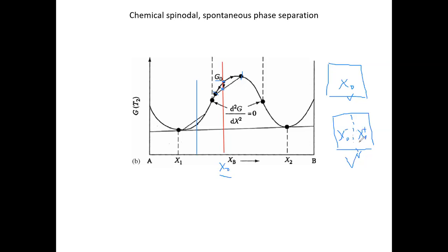Now you can clearly see that if our composition is this given composition, X0, then by separating into these two different compositions, we lower the free energy by this very small amount, which is roughly here. Can we see this? I think this is clear, right? So this sounds good, because the initial fluctuation leads to this decomposition, and it gives you a slightly lower free energy.